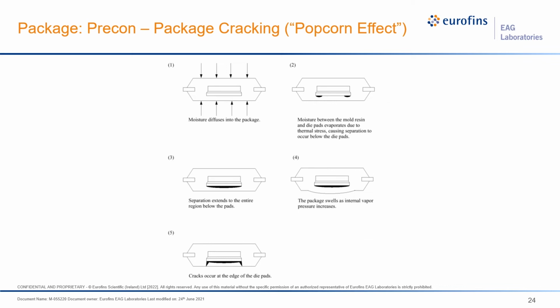Popcorn effect. This slide shows the most common failure mechanism for preconditioning. Here we see in step 1 that during the moisture soak level of preconditioning, the device is absorbing moisture within it. In step 2, this moisture becomes trapped, not released. And then as we go into the solder reflow, the device is heated up to a range of 260 degrees C for the reflow.